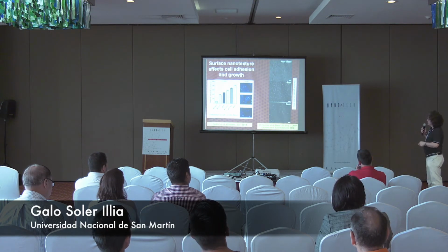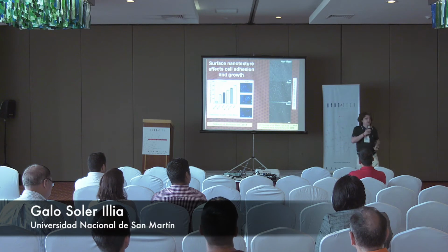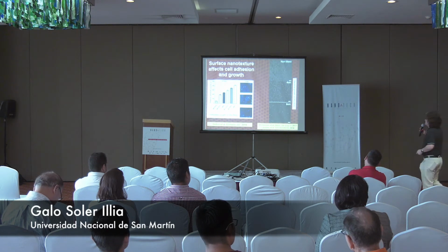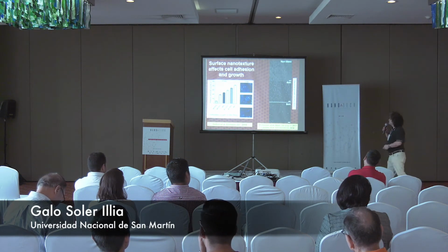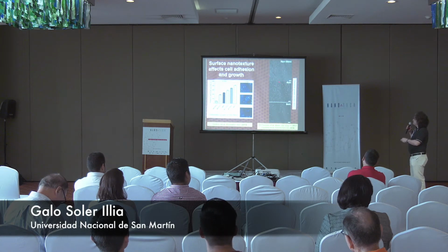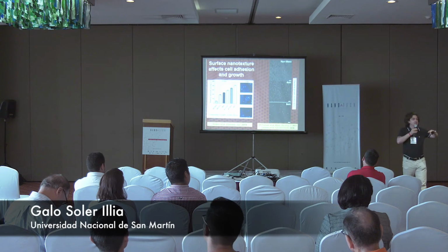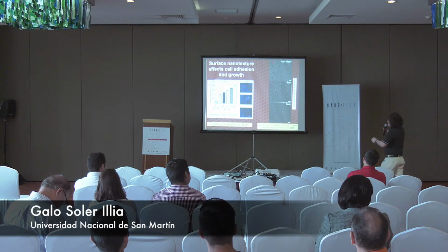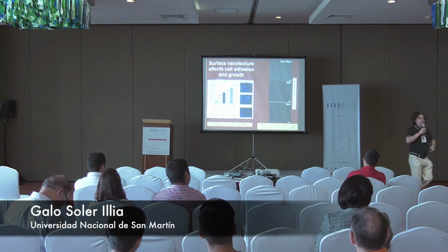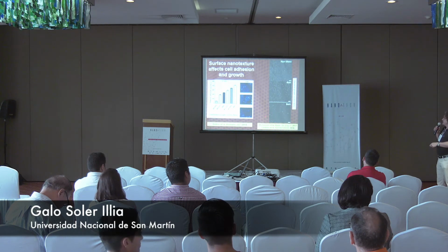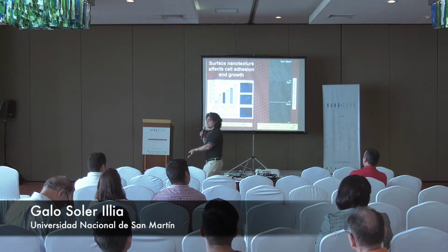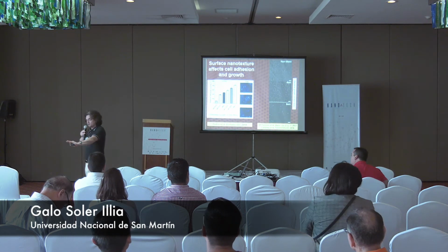Bacteria, for example, Pseudomonas aeruginosa, which is a bacterium that forms biofilms, which is a very nasty way to colonize a surface, which is dangerous in hospitals and bad for industry. Bacteria develop biofilms on surfaces, but when you pattern the surface with this kind of mesoporous film, depending on the pore size, bacteria do not create these biofilms anymore, keep isolated, live their life isolated, and die easily. So this is nice, because you can give a physical signal to a bacterial colony in order to tell the bacterial colony, no parking here.